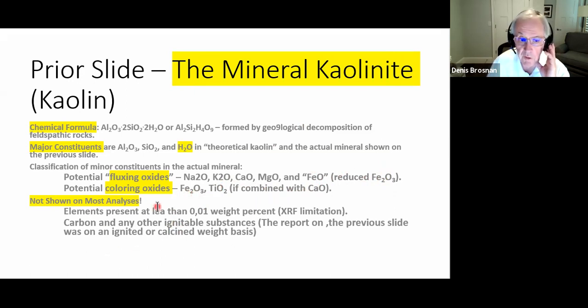So not shown on the analyses that we have were anything less than about 0.01% by weight, or things the XRF is incapable of detecting, like sodium, as I said before. Most people accept the detection limit of XRF units as 0.01. It can be lower. It depends on a lot of factors that are instrumental in nature. We don't show any carbon or other ignitable substances in the composition. So that's typically going to be what we see in a composition.